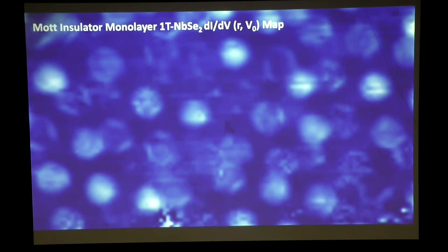Finally, I'm moving away from topography. This is a density of states map. This material, niobium diselenide 1T, is actually a Mott insulator, and many people believe it's a spin liquid. Mike has similar images on a sister compound. And what we believe is that this pattern of dots is where the electrons actually sit at a particular energy. And if you take a Fourier transform of this, you see evidence for a spin liquid in this compound.